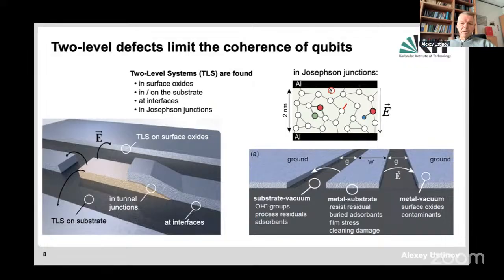So typical material for superconducting quantum circuits is aluminum. And when you make a Josephson junction, you simply oxidize metallic aluminum in a vacuum chamber, forming a few nanometer thick oxide layer. This oxide layer is disordered typically, and then depositing the top aluminum actually does not make it crystalline anyway. So there is a disorder in the oxide barrier, and this disorder can be, for example, due to some tunneling defects, which could be individual atoms in the resource structures or groups of atoms. This could be tunneling bonds, this could be spins, many different types of defects have been proposed.